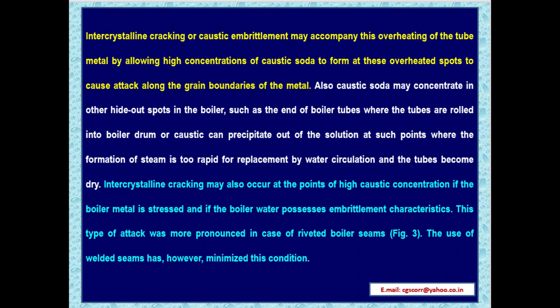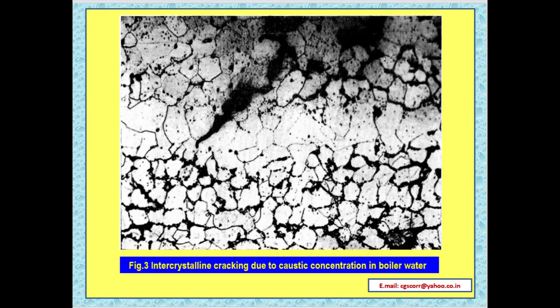Intercrystalline cracking may also occur at the points of high caustic concentration if the boiler metal is stressed and if the boiler water possesses embrittlement characteristics. This type of attack was more pronounced in the case of riveted boiler seams. The use of welded seams has, however, minimized this condition. Figure 3 picturizes intercrystalline cracking due to caustic concentration in boiler water.